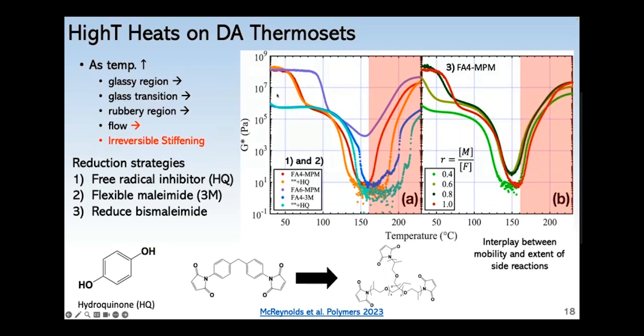So if, for example, you follow along the red curve, which is the Fa4 MPM, and then you follow the orange curve, which has the hydroquinone additive, we can see that it delayed the irreversible stiffening by several tens of degrees. For the second strategy, we synthesized the tris-maleimide compound with a flexible backbone, which is shown by the blue curves in the first plot. And this also worked to reduce the impact from the side reaction.